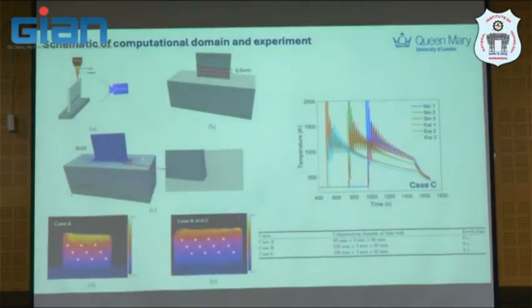And this is how they define the domain. This is a thin wall with the infrared camera here. Then they have 3 cases, which are smaller builds. There is no dwell time here, so each deposition goes on all together, without leaving some time in between. But cases B and C are bigger builds, and one of them has a 5-second dwell time before the next deposition. This is what you can see.